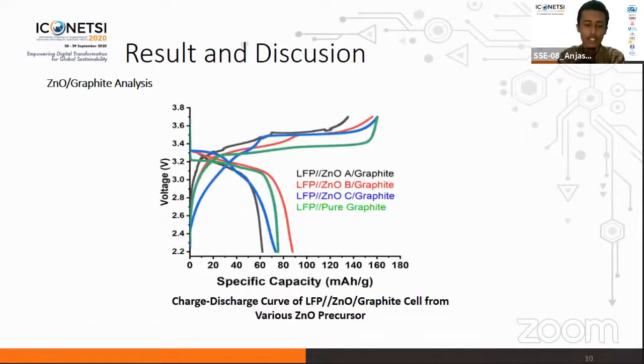And then the electrochemical performance of ZnO-graphite composite from various ZnO precursors was analyzed by measuring the charge and discharge capacity of the LFP ZnO-graphite cell, where the ZnO-graphite samples were applied as the anode material. This figure displays the charge and discharge curve. The specific capacity is measured based on LFP weight basis.